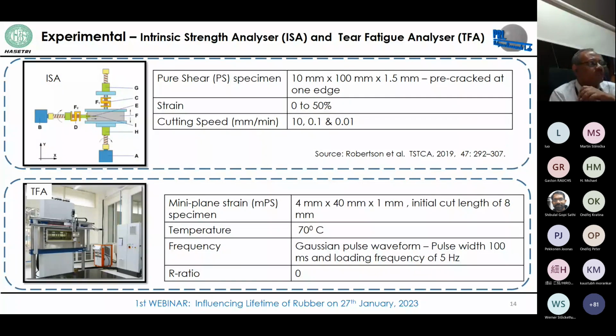So different experiments were carried out, all on instruments made by Coesfeld. The first was with the intrinsic strength analyzer. There we used a pure shear specimen of 10 millimeter by 100 millimeter by 1.5 millimeter thickness, pre-cracked at one edge, and strain percentage was 0 to 50%, so that we have different tearing energy levels, and cutting speed was kept at different speeds like 10, 0.1 and 0.01 millimeter per minute.